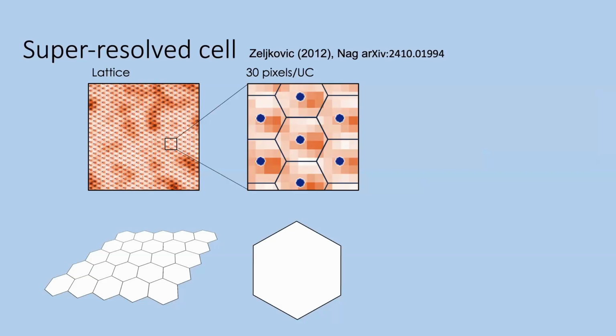So what you see on the top left is the dI/dV map taken over a surface of, actually, a different kagome material, just for the sake of demonstration, that we've measured. Basically what we do in STM is measure pixel by pixel over the surface, but our grid is never commensurate with the crystal structure, not in its size and not in its symmetries. We usually use just a cubic grid, and here it's a kagome lattice, which means that at every point we're probing presumably the same unit cell at a slightly different point. And we do it time and again.